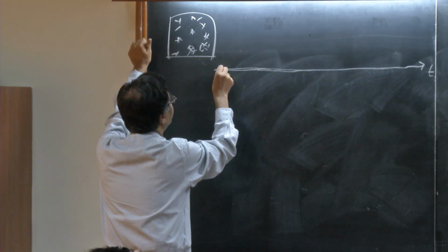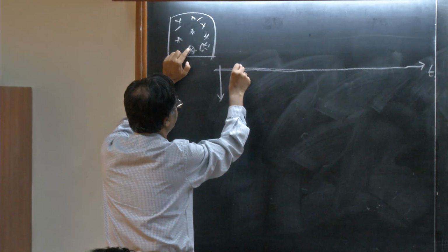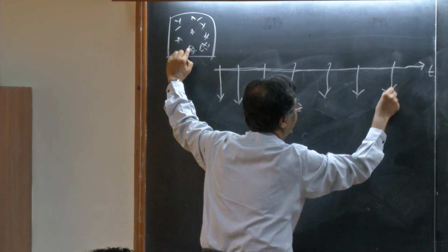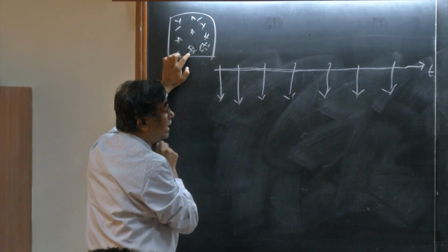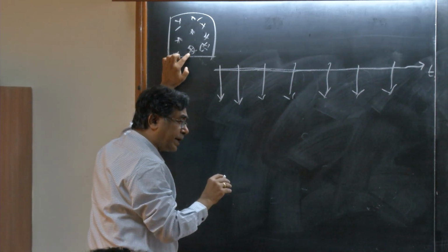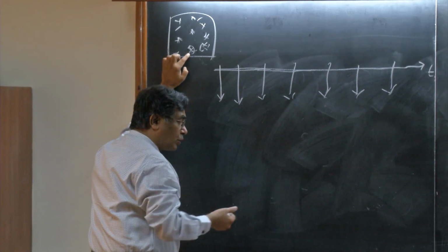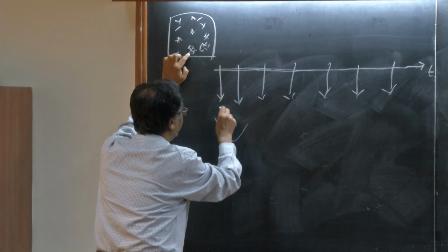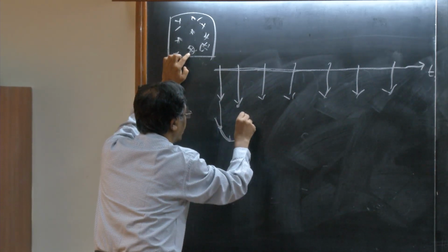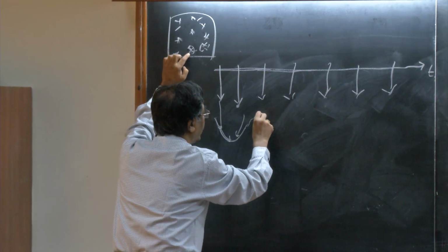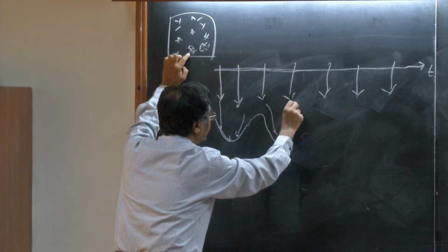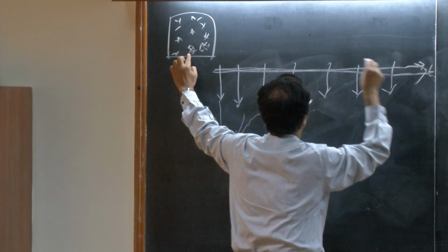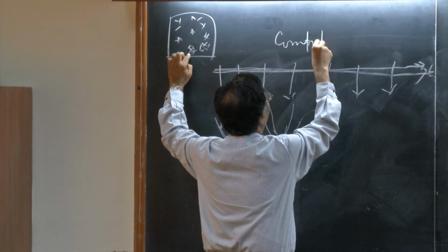Now what I do, at selected intervals, I remove all the kinetic energy. Then what I get, and I do it in such a way that I get the local minima. That means I do it slowly and carefully, so that I don't cross a barrier. If I do that, then these two will go to one minimum. So this one will come here, this one will come here. Then by that time it might have crossed over to another minimum. So by going through the trajectory, it's a computational technique, but very common and very easy.